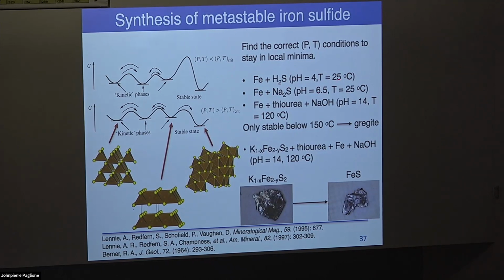In the geochemical literature, there's actually a bunch of methods to do this. These are two somewhat old, 1990s and 1964, literature routes to make it, because it's a naturally occurring mineral, iron sulfide in the structure called mackinawite. And these are different routes to get polycrystalline mackinawite, and this isn't even hydrothermal. This is just at room temperature. We can do these reactions to get mackinawite. But we've also found that you can do this hydrothermally.